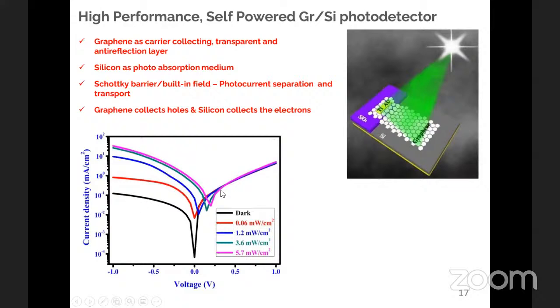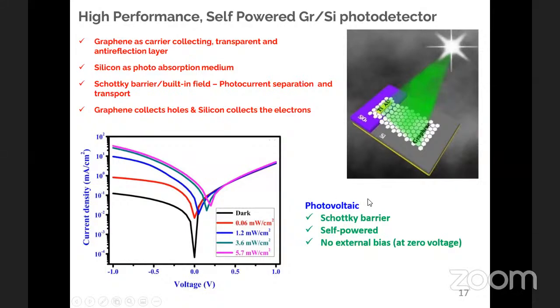This is the black one, which shows the dark current. When you shine the light, you can clearly see the increase in the photocurrent of the devices. So the device in fact performs as a photovoltaic device, like a solar cell. It acts like a Schottky junction solar cell, based on a Schottky barrier, and it is self-powered because it's photovoltaic. That means you don't need to apply any bias to generate a photocurrent.